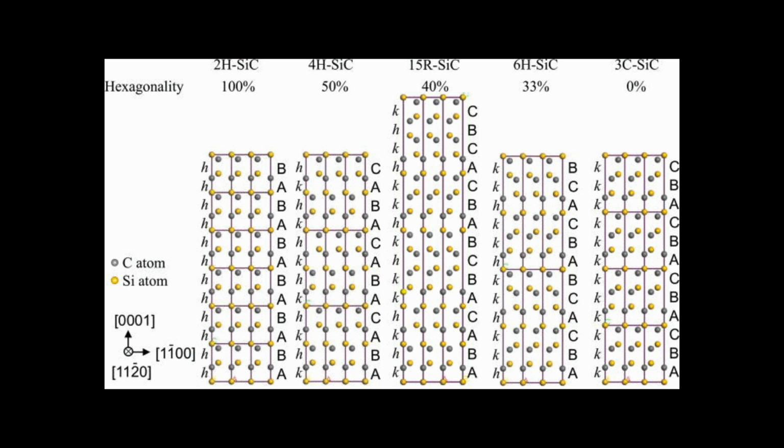Made up of equal parts silicon and carbon, there are over 200 known crystal polytypes, variants in the silicon carbide multiverse. It is not fully understood why there are so many polytypes, but they all have their own unique physical traits. But only 3 can be used for electron devices: 3C, 4H, and 6H. 3C wafers are not commercially available due to instability at high temperatures, so, practically, our choices are just 4H and 6H. While people have studied the 6H variant, most commercial research is consolidating to 4H.